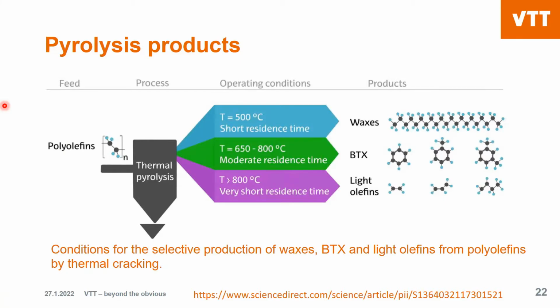If you have a moderately high temperature, somewhere between 650 and 800 Celsius, with moderate residence time, meaning a bit more residence time than a short residence time, and by short residence time I mean between 1 second and 2 seconds, and moderate residence time can be more than that, if you use that at high temperatures, then you get aromatic compounds. And then if you have very high temperature, more than 800, and very short residence time, then you get gases, which are basically rich in light olefins.